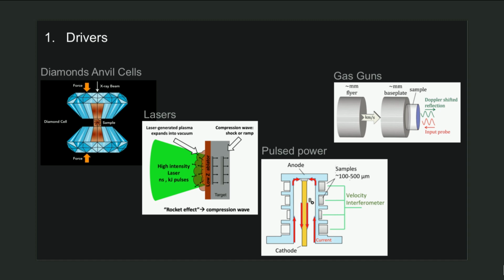Laser compression is achievable when you focus the laser onto the back of your sample, and it creates a plasma. A target surface that is low in Z, low in atomic number, makes it easier to create a plasma. You don't have as many electrons to pull off. And so as you create that plasma, the plasma expands backwards and sends an equal and opposite force into the sample. And this is how we compress materials. If you do this with a lot of power all at once, we can send a shock wave through the sample, but you can control the laser pulse shape that goes into it, and then bleed in the energy slowly and not actually ever reach shock compression.